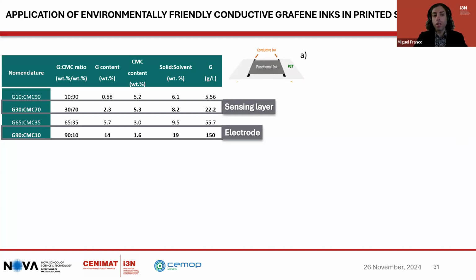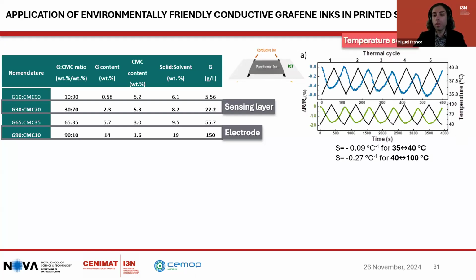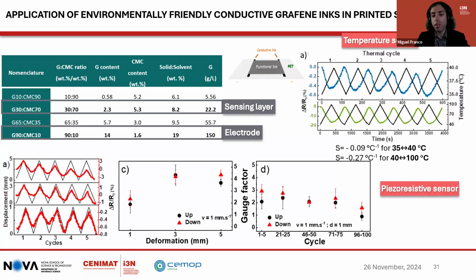The sensors can work as a temperature sensor, where two ranges of temperatures were tested, one between 30 and 40 degrees Celsius to estimate human body temperature, and then between 40 and 100 degrees Celsius for automotive applications. Also, these sensors can work as piezoresistive sensors with a gauge factor up to 4, higher than ferrous based composites.